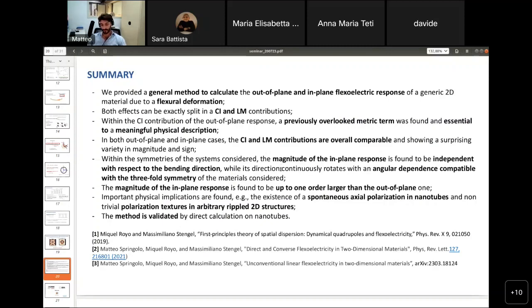In addition, we find that generally for both out-of-plane and in-plane responses, the clamped-ion and lattice-mediated contributions are overall comparable. And we find also that they are described by a surprising variety of magnitude and sign. We then calculated the in-plane response and found that its magnitude is independent with respect to the bending direction, and that its direction actually rotates with a behavior that is compatible with the threefold symmetry of the system.